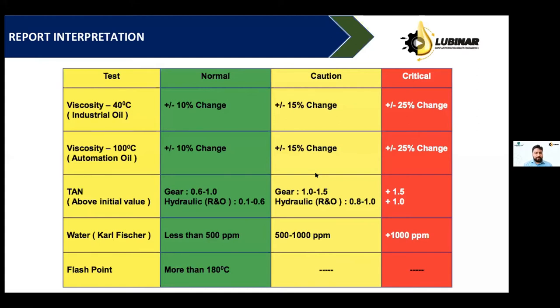Laboratories may suggest purification or reclamation of oil. For high-level tests like wear debris analysis, we can identify exactly which machine parts are wearing out, causing oil deterioration or contamination. For viscosity, plus or minus 10% of standard viscosity is acceptable as per lubricant suppliers. For an oil analysis program, plus or minus 15% is a caution threshold, and plus or minus 25% is critical — requiring immediate action. Viscosity can be checked at 40°C or 100°C depending on the oil used.